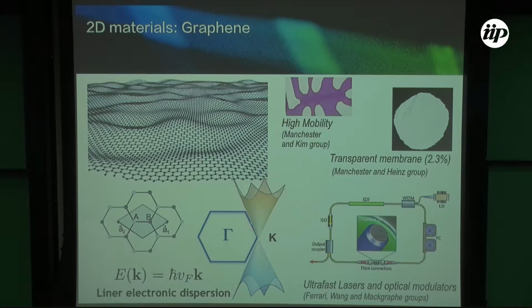I don't need to go into details, but since I'm here, let me say that graphene was the first 2D material that was isolated. So we have the graphene sheet. It has very different properties. We have a high mobility. It's a transparent membrane, with about 2.3% of light absorption. You have the Dirac cones, and it has also found use as a saturable absorber for ultra-fast lasers and optical modulators and so on.